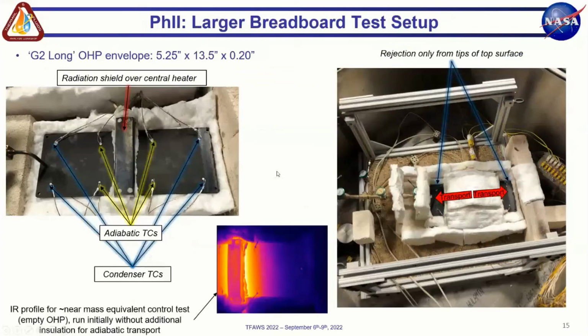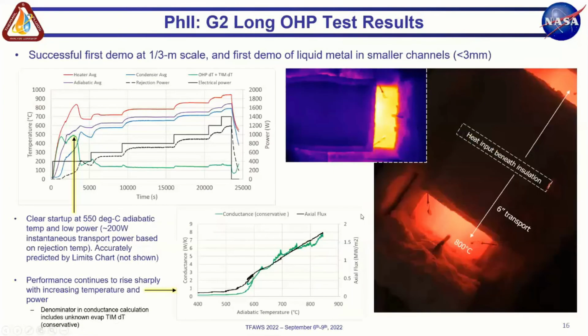Excellent. Okay, so our last breadboard geometry, these planar geometries we tested, was significantly larger, 13.5 inches long, operated in a similar manner. And you can see on the right where we put on some MLI insulation to provide an adiabatic actual transport distance, where we have a remote condenser. So center heated, it's got a transport on the order of 6 inches to a net rejection surface. This worked really nicely, just like the 6-inch scale parts as shown by the IR and the visible here. Again, heat input, about 6-inch transport, able to drive heat out to an 800C condenser.